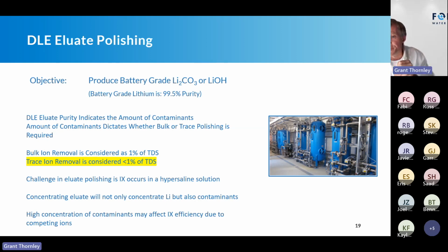Now, depending on the operation of the DLE, if it's able to produce a high purity DLE eluate, then that's great. Then really it's trace polishing, meaning I've got a lot of lithium and a little bit of contaminants. Whereas bulk means that I've got a lower amount of lithium, but a higher concentration of contaminants, so I've got a bulk of contaminants I have to remove. That's a common terminology that we use in DLE polishing. Is it a bulk contaminant removal or trace contaminant removal that I have to accomplish? By definition, bulk ion removal is considered anything greater than 1% of total dissolved solids, and trace ion removal is anything less than 1% of TDS.